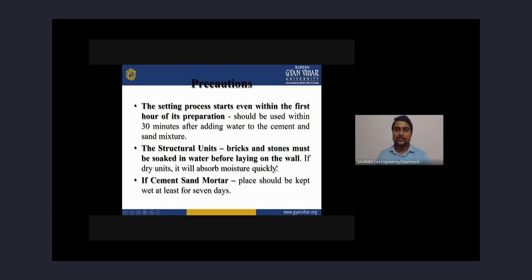Now there are some precautions for the making of cement mortar. The setting process starts even within the first hour of its preparation, so it should be used within 30 minutes after adding water to the cement and sand mixture. The structural units, bricks and stones, must be soaked in water before laying on the wall. If a dry unit is used, it absorbs moisture quickly. Cement sand mortar in place should be kept wet for at least 7 days.